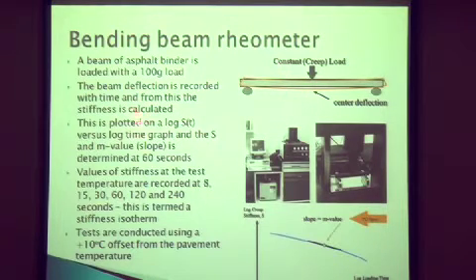So bending beam rheometer, what we have is a very slender beam. This is a picture of the apparatus. I know you have this apparatus in your laboratory here. And what it does is it very nicely defines the stiffness in a low temperature region. We actually collect the stiffness for 8 seconds, 15, 30, 60, 120, and 240 seconds. Normally speaking, we only use that 60-second information and we throw the rest away. If you use that full information, you actually can define the rheology of the binder in a very good manner. So it's actually a very good rheometer, does a very nice job in defining the rheology in the high stiffness region.